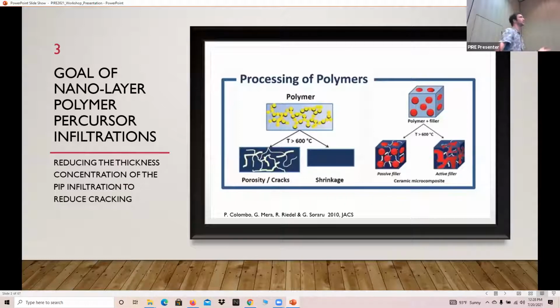So diving right into our NANO-LAYER system that we're working on, we need to look first at the polymer infiltration process, the PIP process. When we do a first round of PIP infiltration, we get lots of cracks. As we heard from Starfire, you can go up to 6-7 recycle processes with SMP10, for instance, and you have lots of different cracks in that. Now, through that process, it can be kind of difficult to fill all of those cracks.